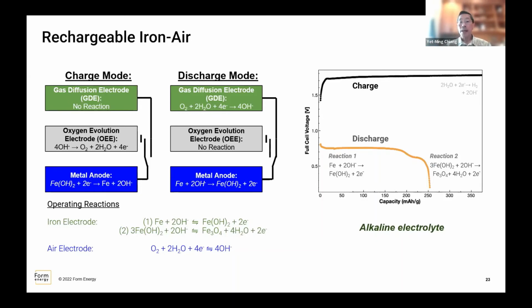Right? And in this case, this comes from the fact that at the iron electrode, the potential is very close to the hydrogen evolution potential for this system. And so you put some of the electrons in charging into the generation of hydrogen. So that needs to be managed. And that's one of the reasons for the round trip inefficiency, the Coulombic inefficiency. The second is the gap you see on the voltage scale, the vertical scale, between charge and discharge. And that's a voltage inefficiency. And that's primarily due to overpotentials necessary at the air electrode.